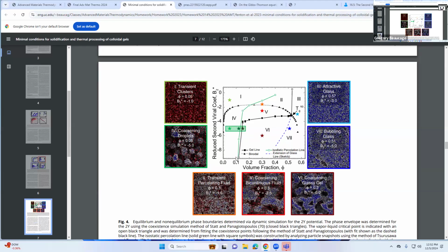And then I think the squares are his actual gelation measurement. So he gets those squares by doing this oscillatory SAOS, small amplitude oscillatory shear rheometry. So he's got a disc on top and a plate on the bottom, and he's going to oscillate this thing at like 1 degree oscillation, and he's going to go across different frequencies.